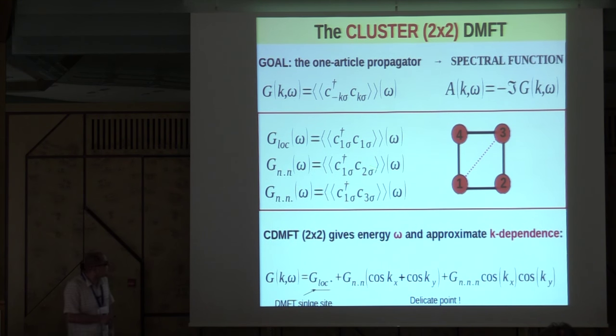What we have with respect to the single site is that we don't have just the local Green's function. We have all the propagators within the cluster. So in this case, I will have a nearest-neighbor Green's function, and a next-nearest-neighbor one, which will be the diagonal one. With these essentially three functions, I can reconstruct a k-dependent Green's function. Of course, this is an approximation. This is not even exactly what we are doing. I didn't want to enter the details, so it's a delicate thing to do. As a matter of fact, this works well. If you think of this as a truncated Fourier expansion, you would like to have as many Fourier coefficients as possible. So the bigger the cluster, the better your approximation is going to be. So it's a very well-defined problem. How good is, for example, the 2x2 plaquette, which truncates already at the fourth term?